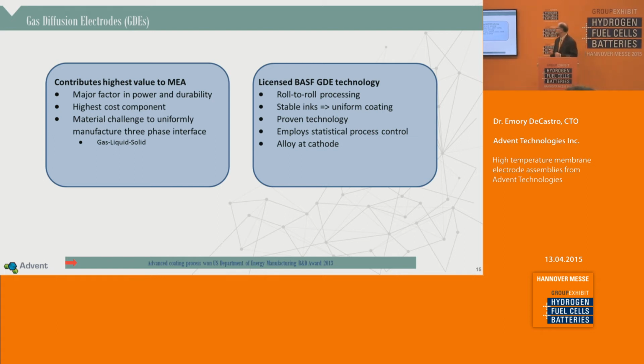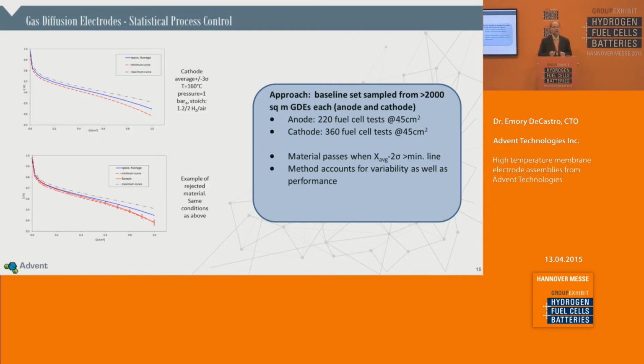using very stable inks, uniform coatings, proven technology, and because of the high volume that has been manufactured using this technology, we can employ statistical process control on the gas diffusion electrodes so we know if it is good quality when we make the MEA. And that is shown here on the left, and I'll just quickly go through the example. On the upper left is a polarization curve. The blue line represents the average of over several hundred tests over many thousand square meters of gas diffusion electrode for the cathode. The dotted lines represent your plus and minus 3 sigma. So this really represents the manufacturing capability of the process.